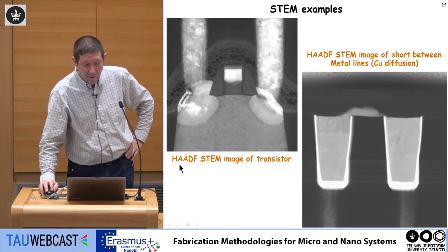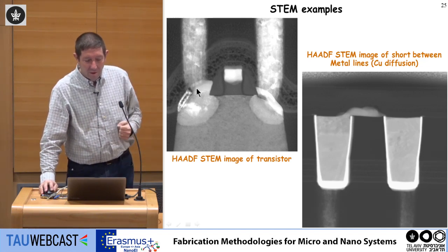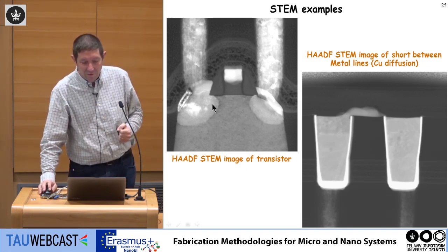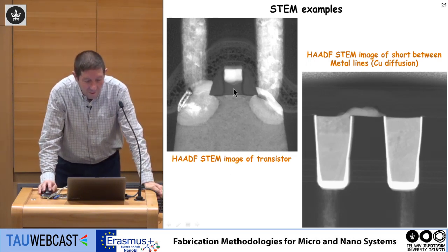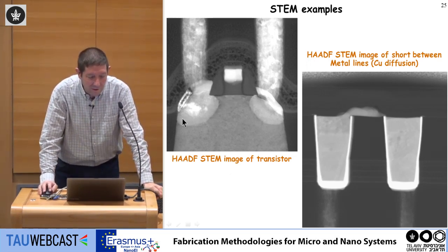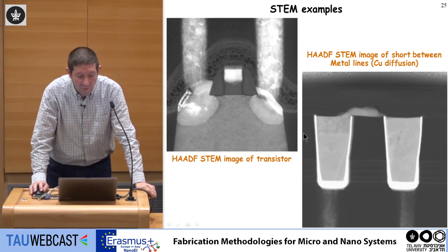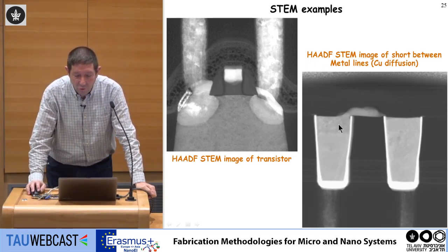So this is a HAADF, high angle annular dark field STEM of a transistor. This is a transistor. This is the polysilicon, silicide, source drain and the contact. And this is the STEM image of a short between metal lines. This is a metal line. This is copper metallization. This is the barrier.